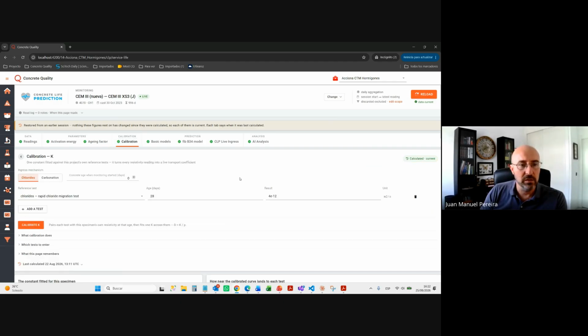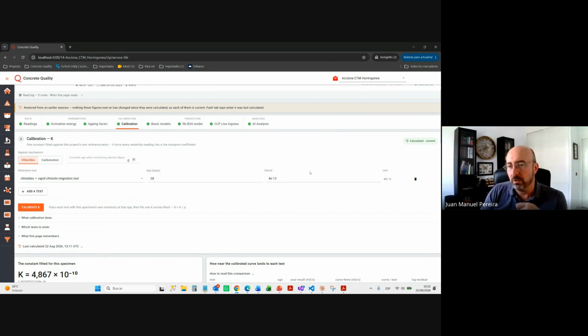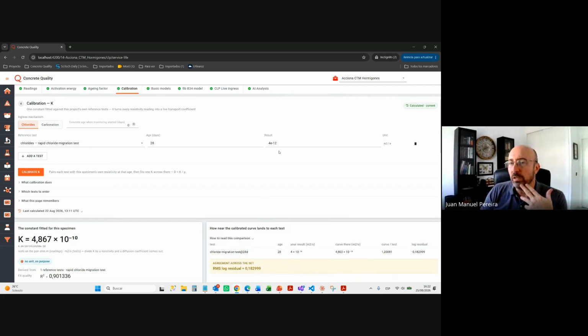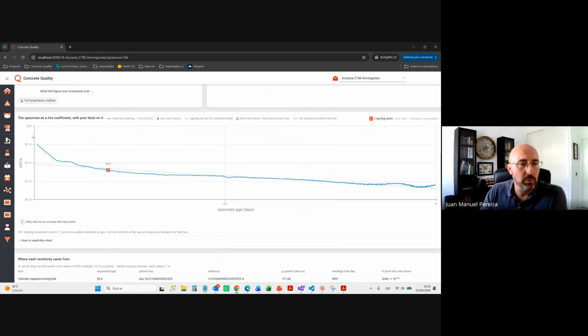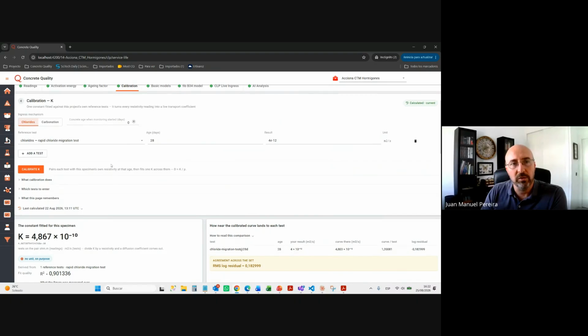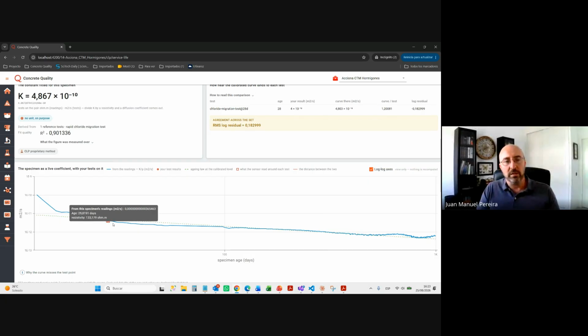This calibration works like this: if I have one chloride migration test at 28 days with this result, we can add as many as we need. If we have, for instance, 90 days, 180 days, whatever, we can add all of them, and the system will automatically make the best fit through all of these points. So basically we have the shape of the curve with this aging factor, and here we have the level. With these two things and the activation energy, we can transform this reading of electrical resistivity into whatever unit, whatever type of measurement you're doing in your lab. If this is RCP, we can transform this reading into RCPT, real time. If this is chloride diffusion coefficient, we can transform this into diffusion coefficient, real time. And you can use that in the models, and this is what we do.